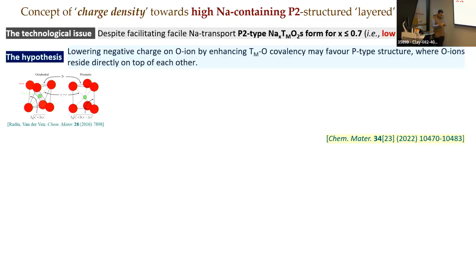So this indicates that from this one can get an idea that, okay, if my oxygen ions can have slightly lower effective negative charge, then they might like to reside one on top of the other, that is maintain a prismatic coordination, even if I stuff more sodium ions in between them, because of which they come closer to each other. So here the idea is just the reverse of the previous thing. The idea is to lower the effective negative charge on the oxygen ion. And how can we do that?